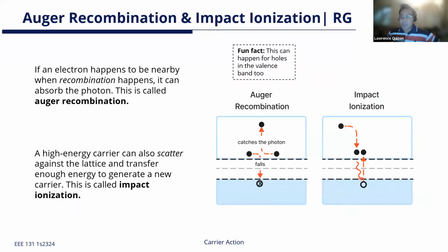the next few types are compound types essentially, no? So they're special situations. One thing is called Auger recombination, no? So when two electrons meet and they bump into each other and both of them are low energy, no? They're low in the conduction band. One of them gains the energy from the collision and one of them loses the energy from the collision, no? So what happens is that one of the electrons gets promoted higher in the conduction band and one of the electrons falls into a hole in the valence band, no? So one of them recombines and one of them goes up, no?